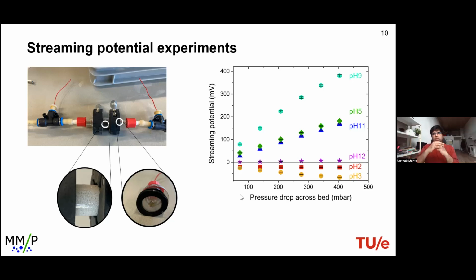Because the surface is net positive, the surrounding aqueous media is negative. And when you push it through the electrode, what we observe is a negative potential across the bed. Contrary, because we're dealing with basic media in the rest of the experiments, we see that the surface is negatively charged, the surrounding aqueous media is positively charged, and therefore we see that the potential is net positive.